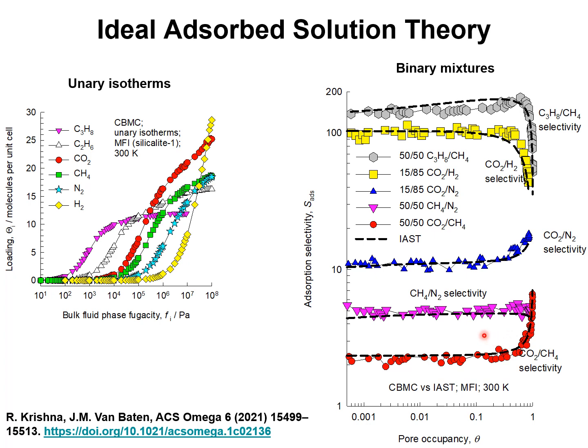So if the unary isotherms for the gas species have large differences in saturation loadings, it is of vital importance to use the IAST and abandon the mixed gas Langmuir model to describe mixture adsorption equilibrium.